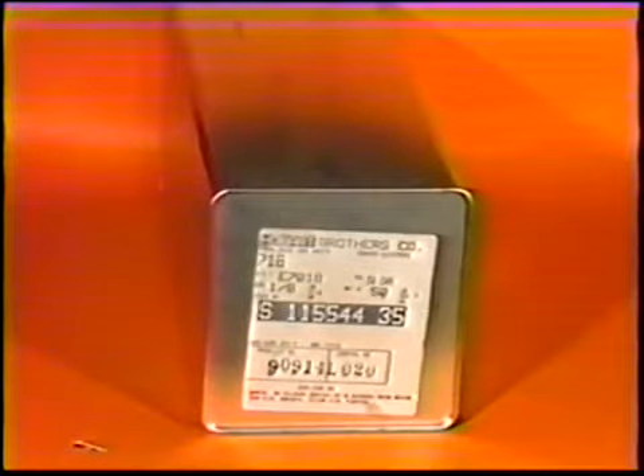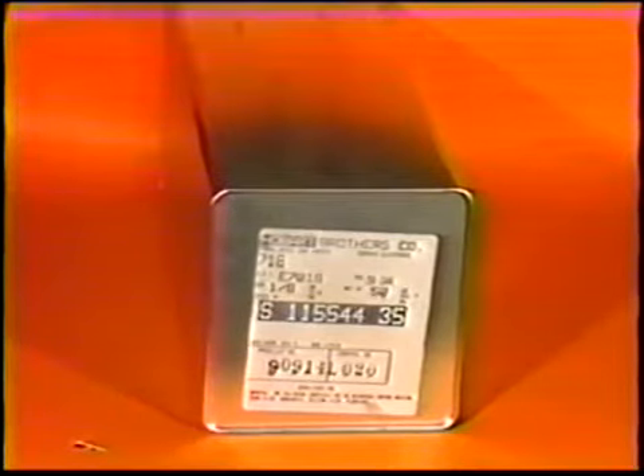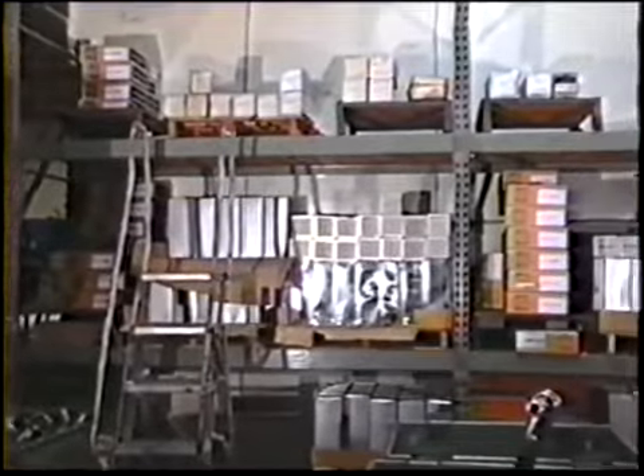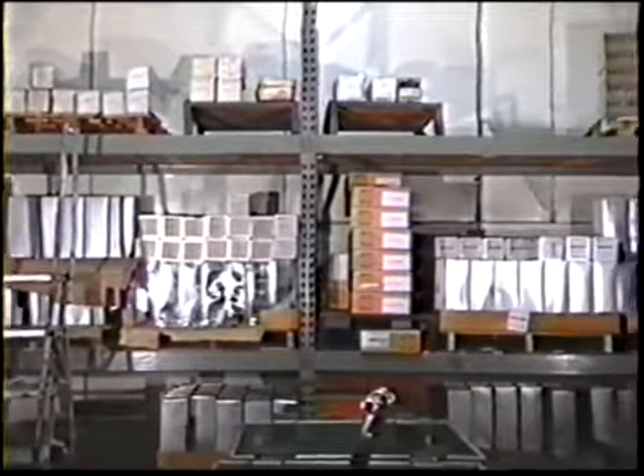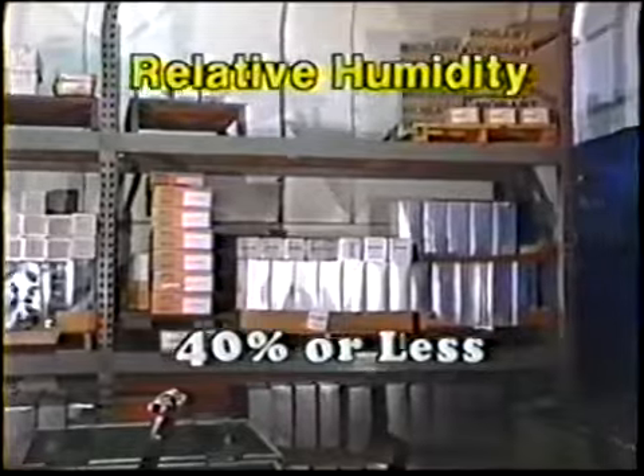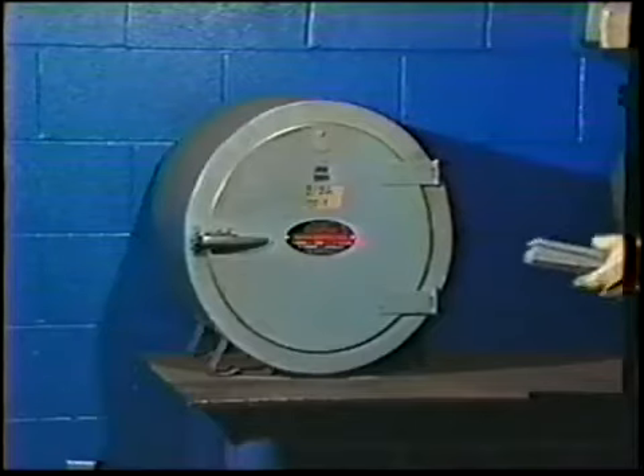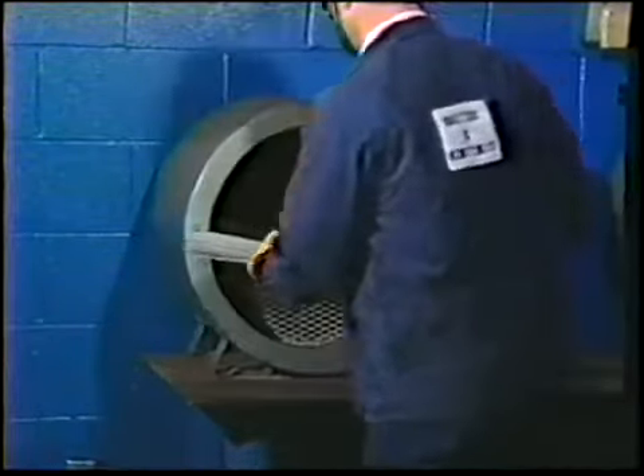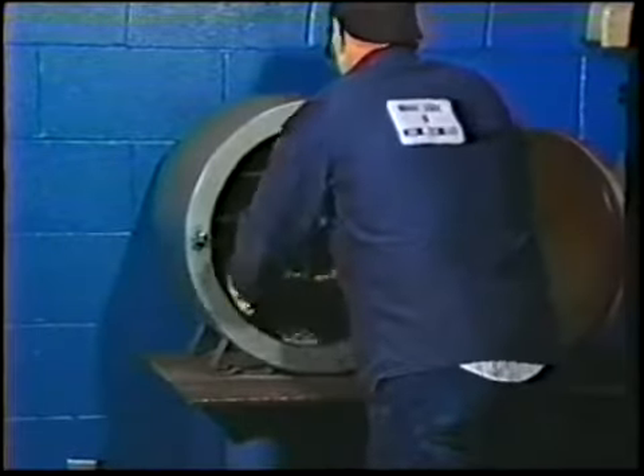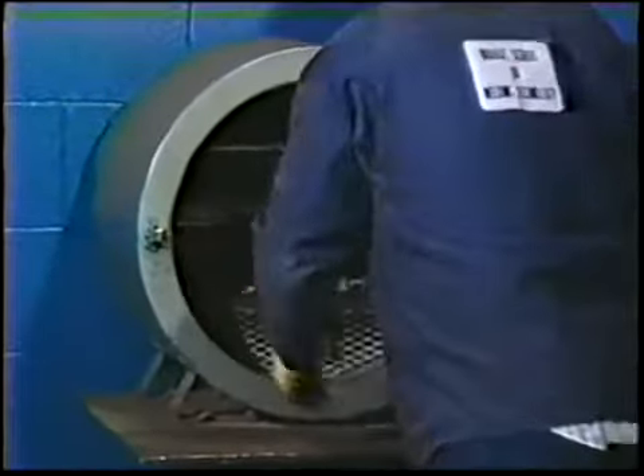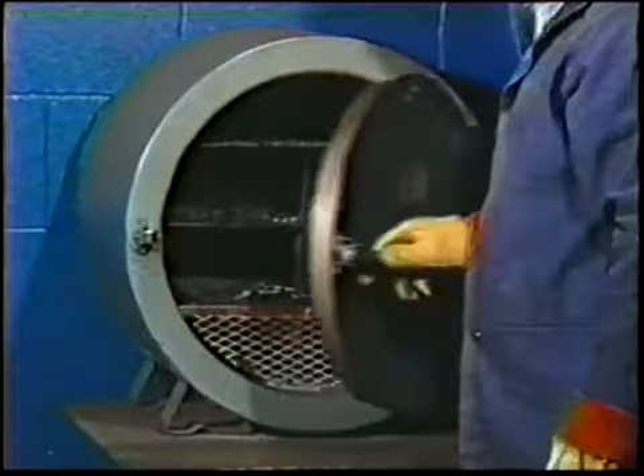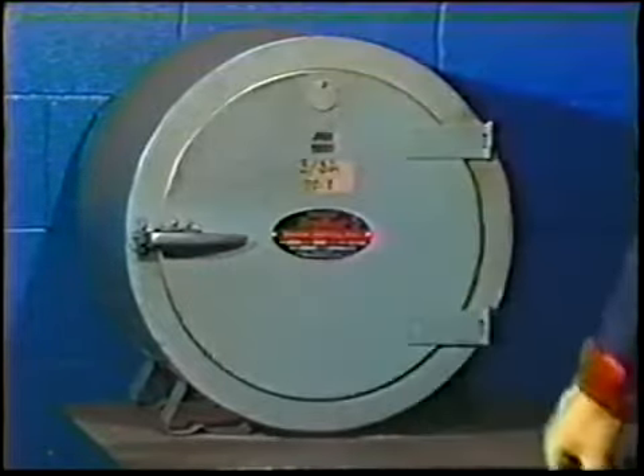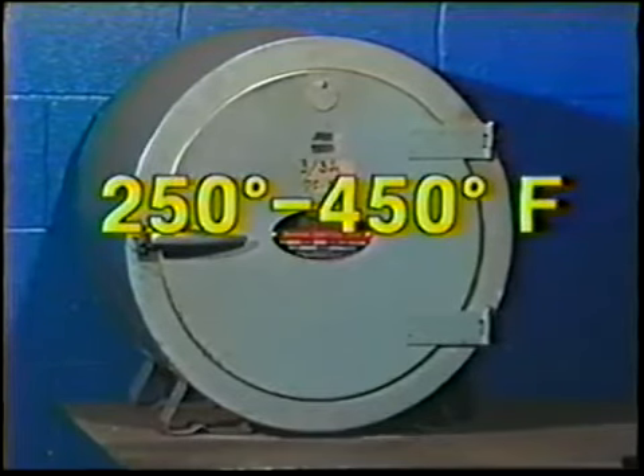Electrodes must be stored in sealed containers in a dry environment to prevent damage by moisture or humidity. Special storerooms should be used, equipped with a dehumidifier to keep the relative humidity at 40% or less. Once the sealed container is opened, the electrodes should be stored in holding ovens, reserved especially for the low hydrogen types, and not mixed with other types of electrodes. These ovens should be maintained at a temperature of from 250 to 450 degrees Fahrenheit.